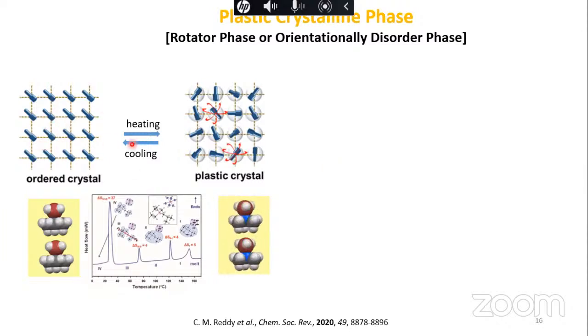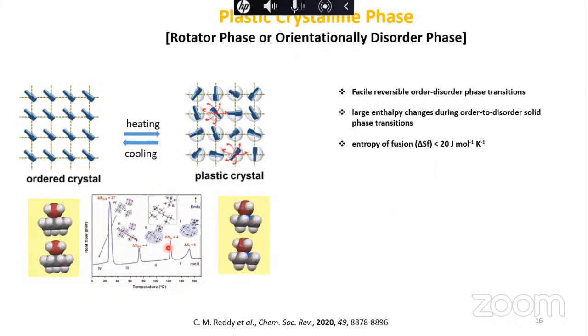Here, since you are rotating all the molecules, all the molecules attain these rotational degrees of freedom in the solid state. So the energy required is normally very, very high for this order to disorder phase transformation. As you can see here, this is a very big jump. And this is a different example, where gradually different modes of transformation, different degrees of freedom, are activated in the crystal. In this particular case, you have a small ion and a big ion. There are two components, so that is why you have different peaks here. But overall, you activate the different degrees of freedom.